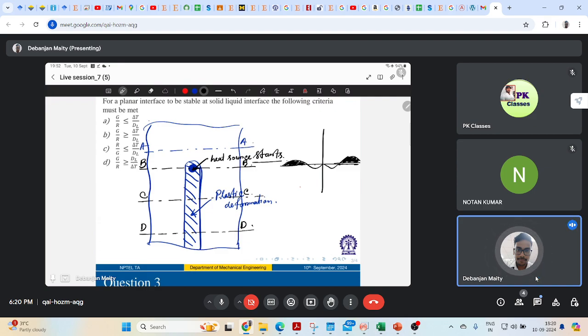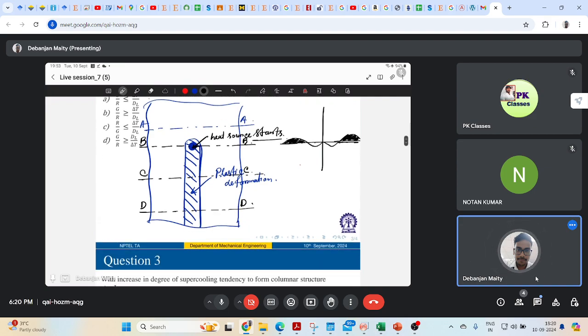Now, as we go away from the melt region, there will be a tendency to increase the tensile residual stress in the center of your weld line. So at section CC, it will be something like this. The black hatched line is my tensile residual stress, and at section DD, more tensile residual stress will be generated over here, right?